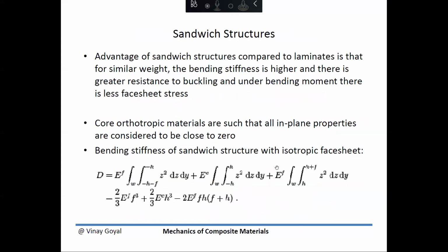So let's discuss sandwich structures. What is the benefit of sandwich structures? The advantage of sandwich structures compared to laminates is that for very similar weight, you can achieve a higher bending stiffness, and there's a greater resistance to buckling under the same bending moment than if you were to have a thin laminate. The way we accomplish that, if you think about it, is that if you have thin laminates and move them further apart and put a weak material in between, what I've really done is increase the bending stiffness quite a bit. And that is shown here.